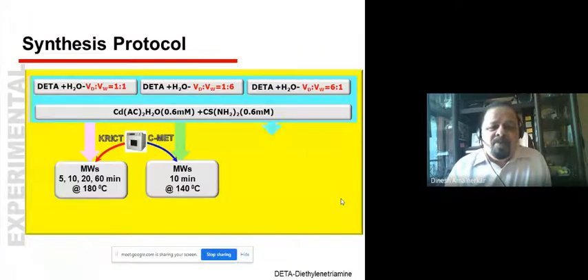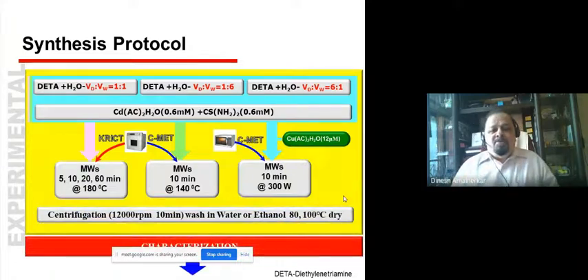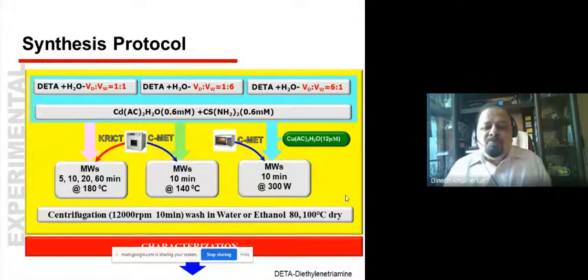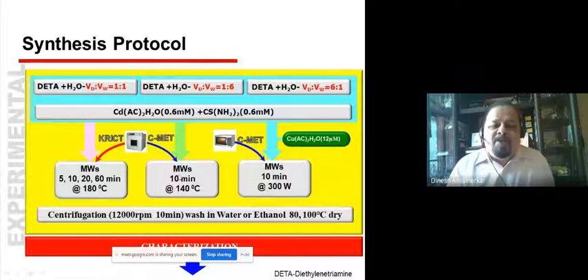Now, our main intention was to create a photoconducting cadmium sulfide. And as I said earlier, with the example, like in the microphotosensor, we got the copper-doped cadmium sulfide. In this case also, we wanted to dope the material with copper. And how could we do that? Well, here we changed two parameters. Instead of the commercially available microwave digester, we have just taken the household Godrej-made microwave oven in our laboratory. And Dr. Manish has very meticulously carried out this work without any accident.